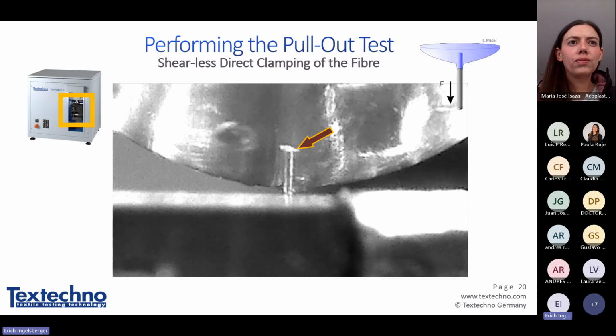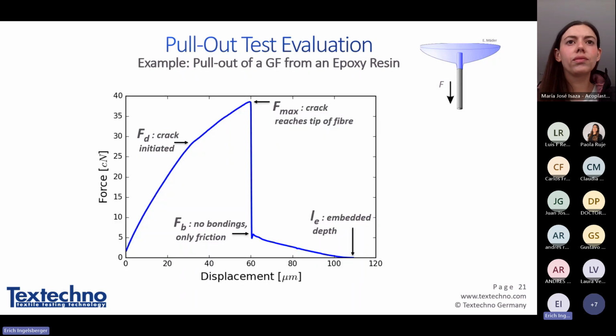While doing this pull-out test, we measure the displacement, that means the movement of the lower clamp, and we measure the force. What results is a force over displacement curve. And if you watch the curve format here, you can see there is a little kink in the force displacement curve, and this is where the crack is initiated.